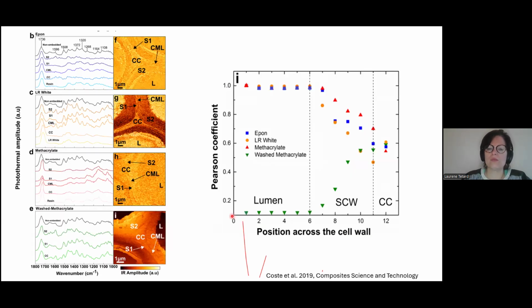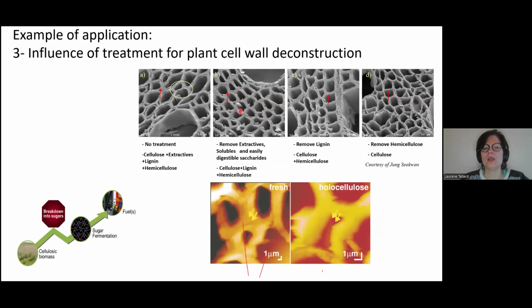So we also confirmed that with nano infrared spectroscopy. We took spectra across all the tissues, and then we did some analysis on the correlation between the signal of the pure resin and the signal we were detecting in the plant cell wall. And we found that all of them were present in our sections. But we continue exploring what we can do with the platform. Some of the things we've done successfully is to study the effect of plant cell wall deconstruction with the AFM, with the morphology and the chemical information.